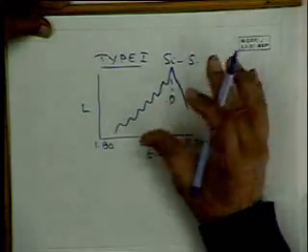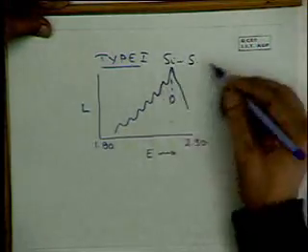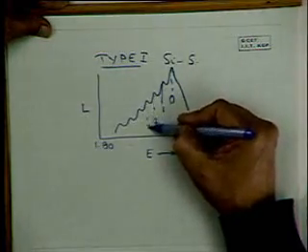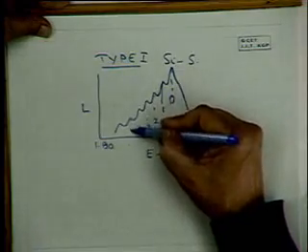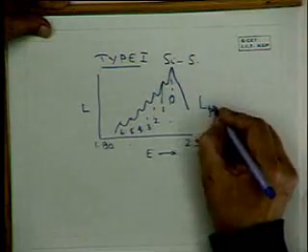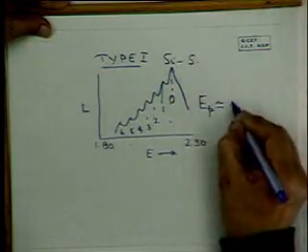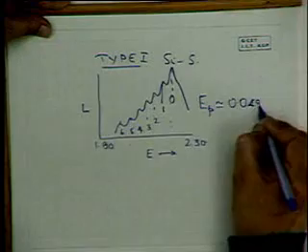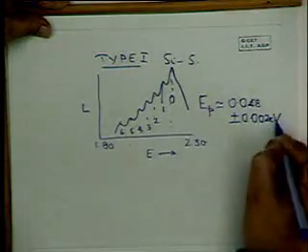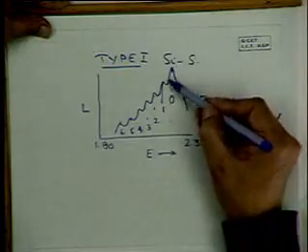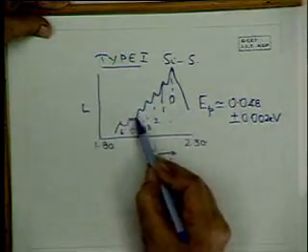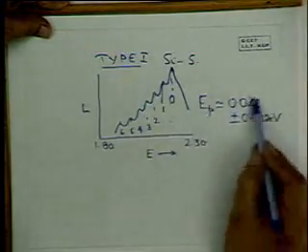Suppose during this donor-acceptor pair recombination, 1 phonon is emitted, we get this line, 2, 3, 4, 5, 6, etc. And since the phonon energies are known, 0.048 plus or minus 0.002 eV, we can identify this, and then we notice that these phonon replicas occur at regular intervals, separated by this phonon energy.